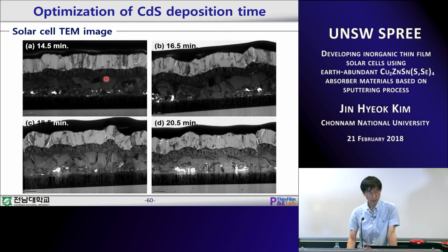And the TEM result shows that the buffer layer gives relatively nice coverage on the absorber layer, even though the absorber layer has some fluctuation and a rough surface morphology. We could almost continuously cover the absorber layer, even though the buffer layer is very thin. When we deposit for 14 minutes, the buffer layer thickness is about 25 to 30 nanometers. Even with such a thin layer, we could form very continuous coverage on the absorber layer. And